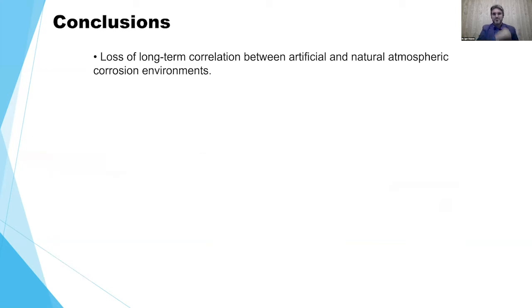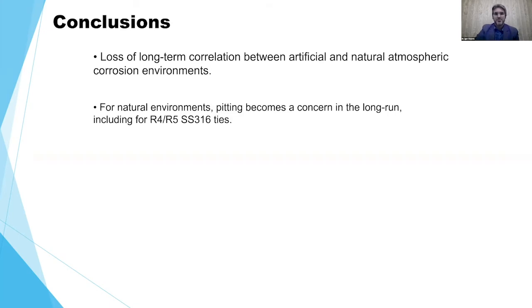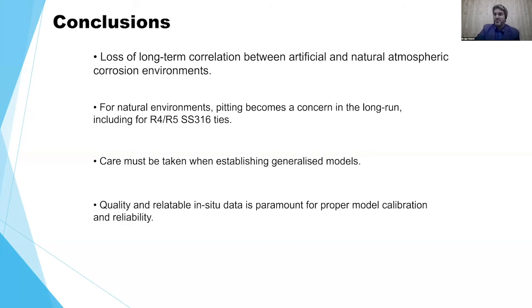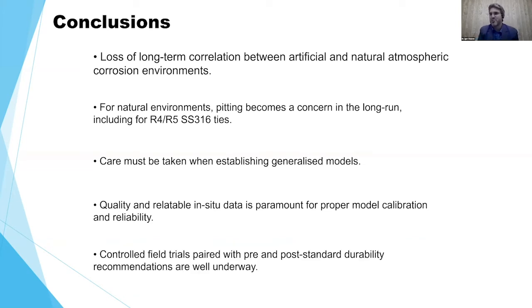So what is the main takeaways? It's very difficult to correlate artificial and natural environments. We need to work on that. For natural environments, pitting becomes a main concern in the long term, right? Particularly for stainless steel ties, which should not be neglected. After all, if there's a hole in the middle of the tie and that breaks, it doesn't matter if it's still intact on both ends, right? It failed its purpose of holding the wall up. You got to be very careful when you're trying to generalize models. We're working on that, but we definitely need in situ data and lots of it to do it. We are continuously working to collect this data and elaborate the model.